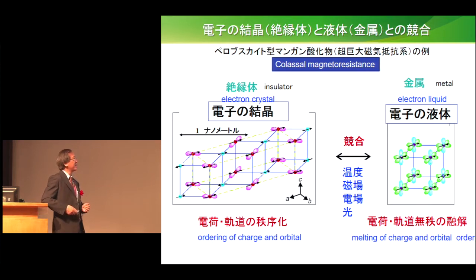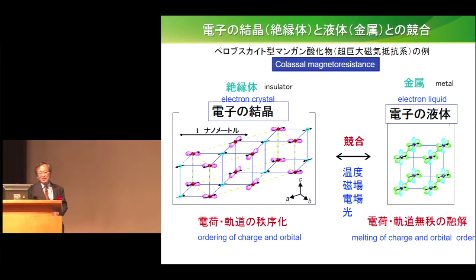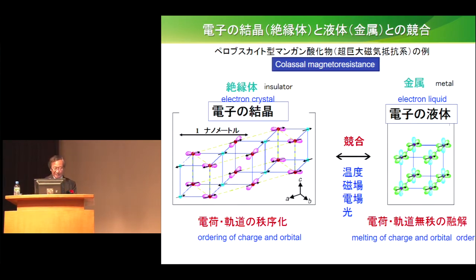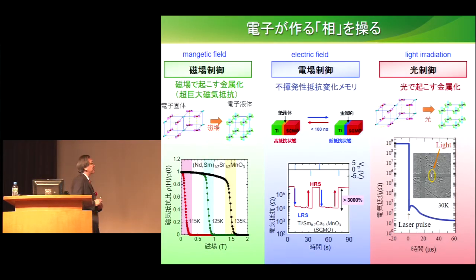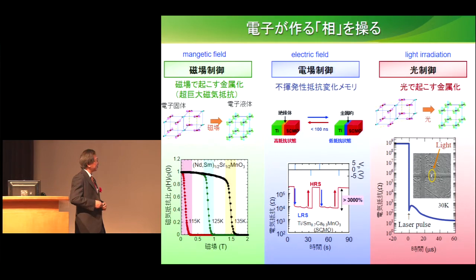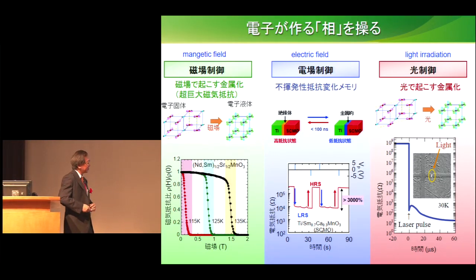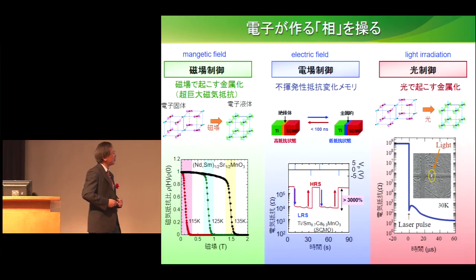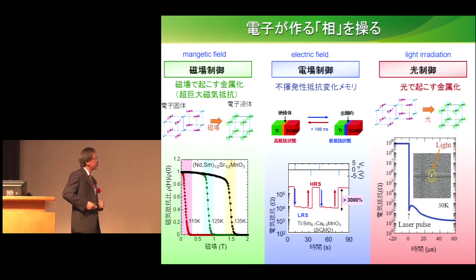This is the ordering of the charge and orbital, and that melts the insulator into the metal, and the anti-ferromagnetism turns into ferromagnetism. And this is the essence of colossal magnetoresistance. By applying the magnetic field, because the solid changes into the liquid, the resistance, which is very high, goes down to a very low level, just like the metal level of resistance. I will come back to the application of electric field. At the interface, insulator turns into metal, and that can be made non-volatile. High resistance and low resistance can be switched.